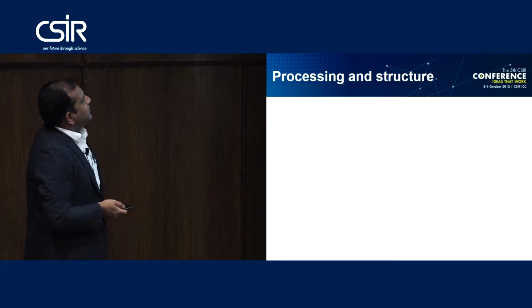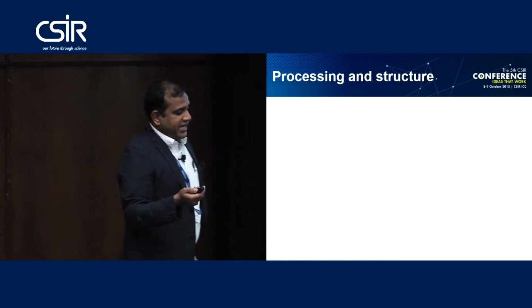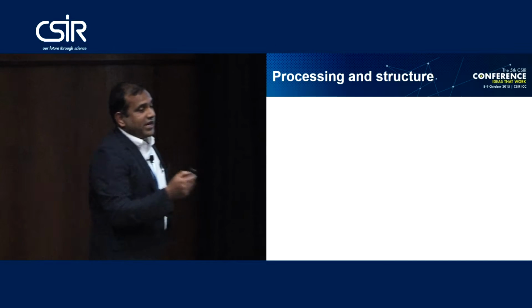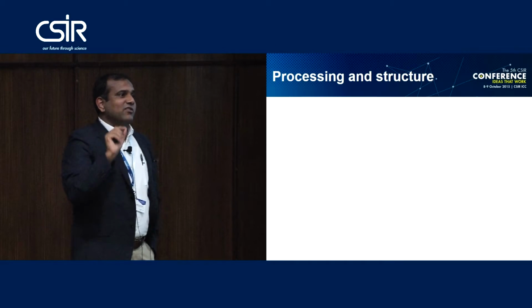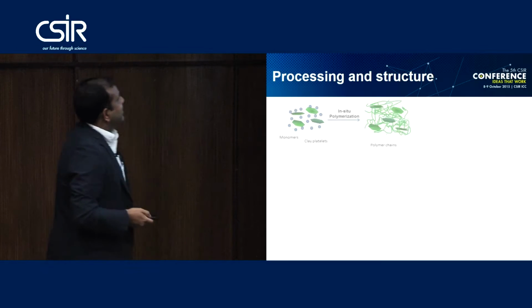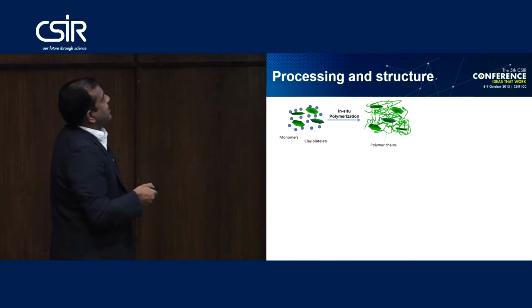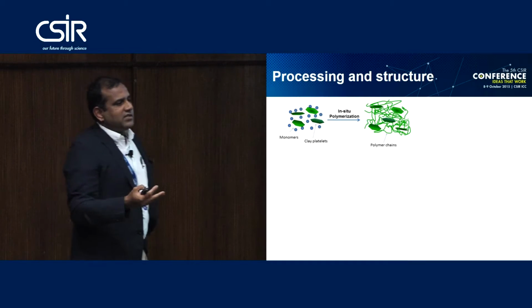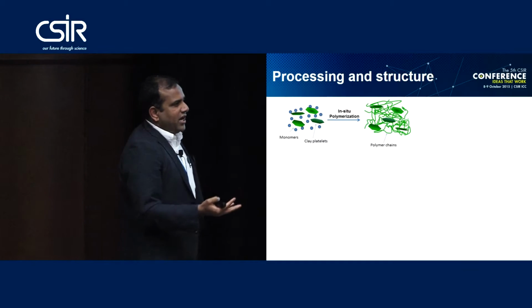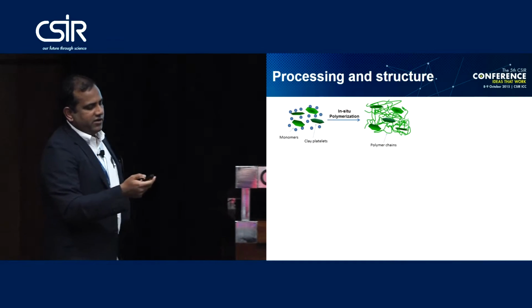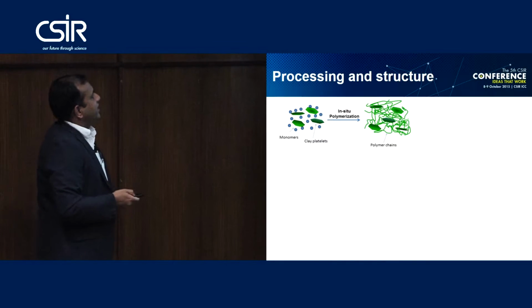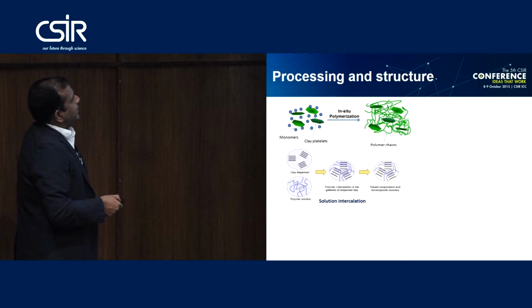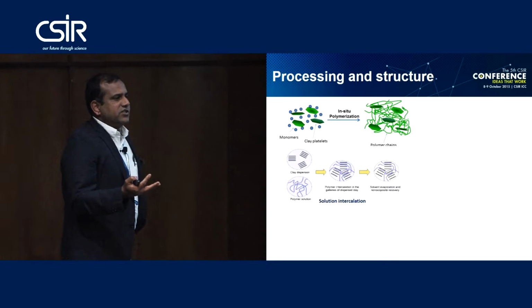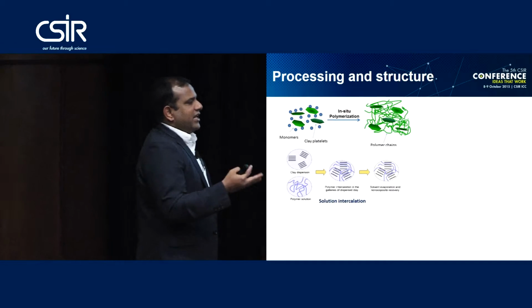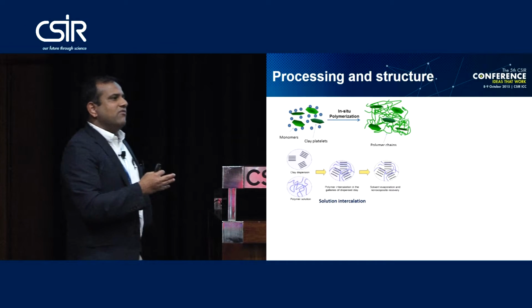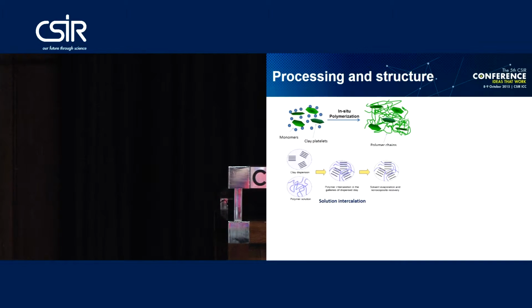So now we can use different kinds of processing techniques. You have organically modified clay, but the ultimate aim, as I said, is nanoscale dispersion in your matrix. You can do in situ polymerization: you disperse your nanoparticles or nanoclay minerals inside the monomer, then you polymerize, and you have one kind of nanocomposite. We generally call this in situ polymerization. Then you can dissolve your polymer in a solvent, disperse your clay platelets in the same solvent, mix, and then evaporate the solvent.